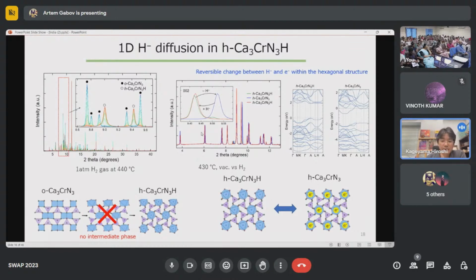Another observation is that when we heat-treat the hexagonal phase under vacuum, the hydrogen is deintercalated as a gas. Then we have the same composition as the initial material, calcium-3 chromium N3. However, the structure doesn't change back into the original orthorhombic structure, but stays hexagonal, which means that the hexagonal chain is retained. Then the DFT calculation and other things show that the electron is located in the hexagonal void by the calcium 6. So this is regarded as an electride material, if you like.